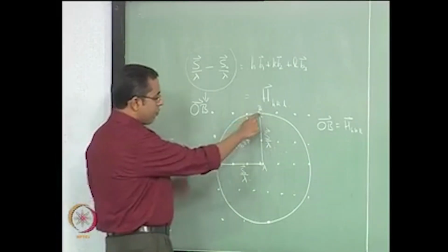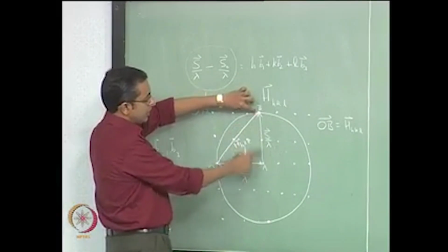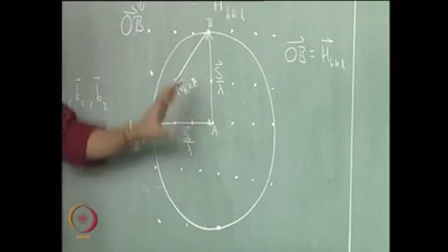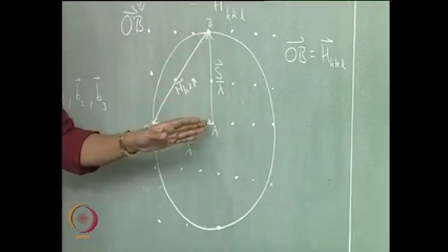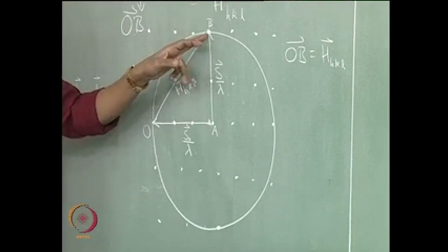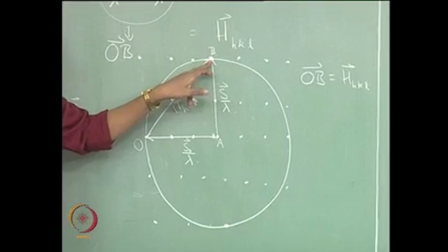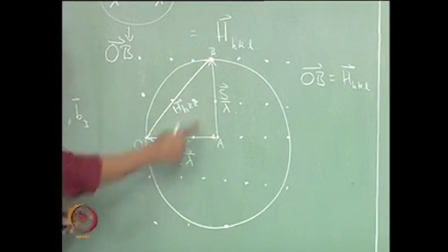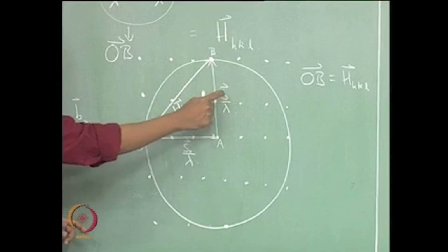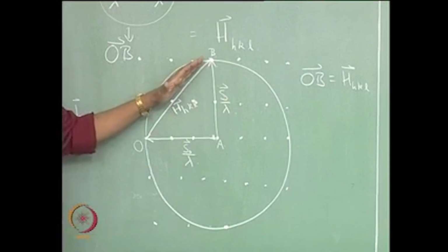And at those particular locations you can now define that wave vector s by lambda, so at that point you not only have the correct magnitude of wavelength, which is 1 by lambda, but you also have a direction such that this difference between the incident beam vector and the diffracted beam vector is a valid reciprocal lattice vector.